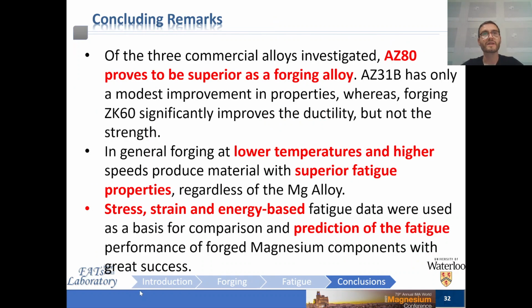So finally, to summarize some concluding remarks here, of the three commercially available alloys that were investigated, AZ80 proves to be superior as a forging alloy. AZ31B has only a modest improvement in properties once forged, whereas forging ZK60 significantly improves the ductility, but not really the strength. However, AZ80 improves across the board and is the best overall compromise of improvement as well as ability of achieving a component while forging.